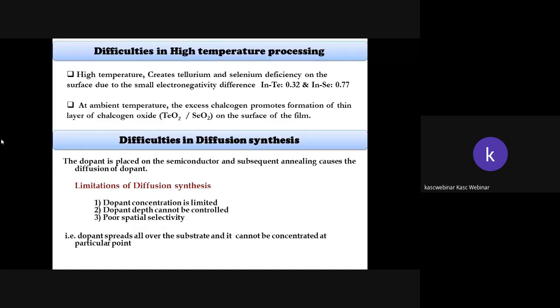At the second part, at ambient temperature, the excess of chalcogenide is present in the sample, which promotes the formation of a thin layer of chalcogenide oxides. Instead of forming this metal chalcogenide sample, we may expect the chalcogenide oxide over the surface of a sample, like tellurium oxide or selenium oxide.